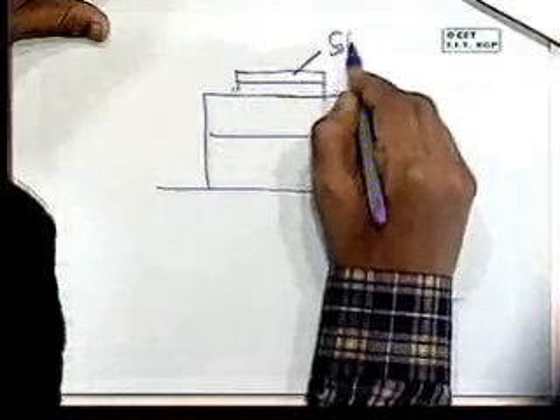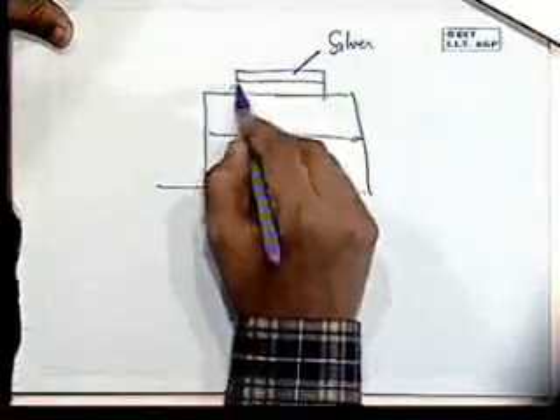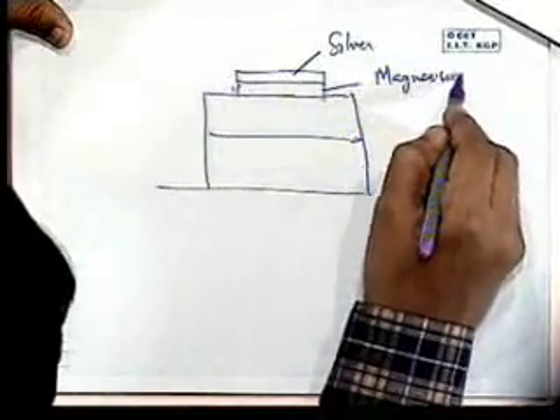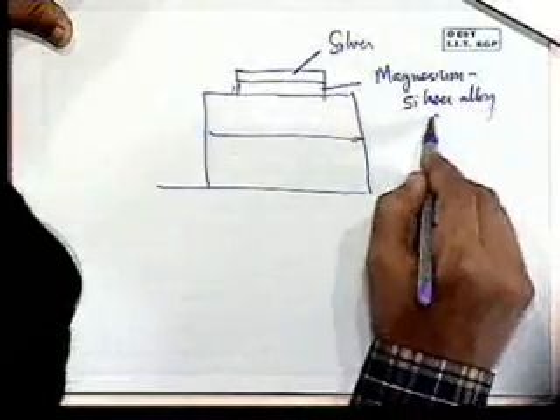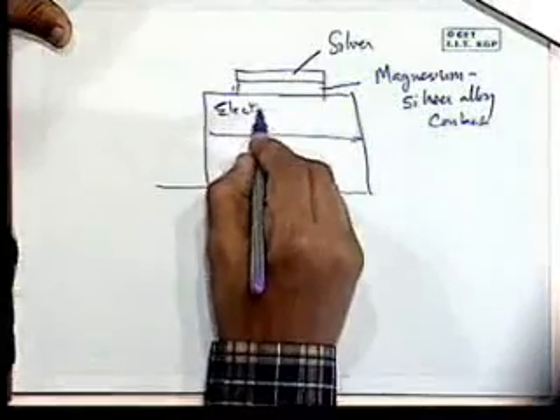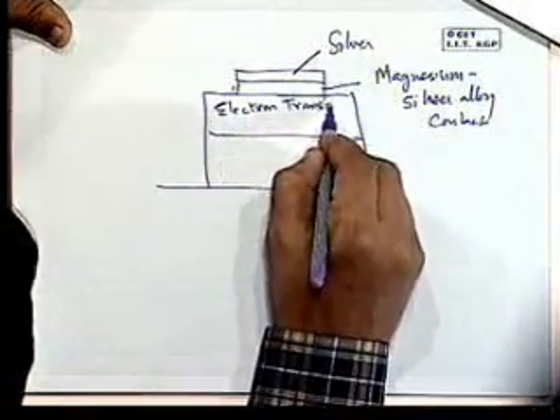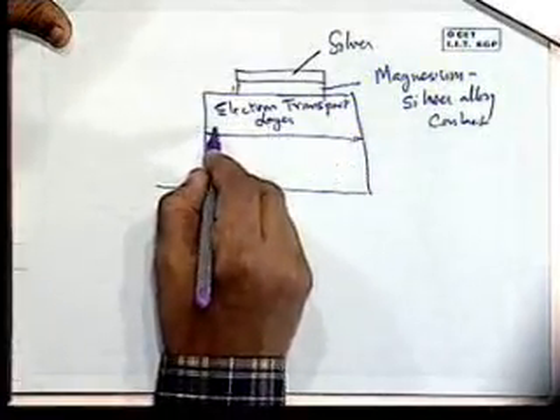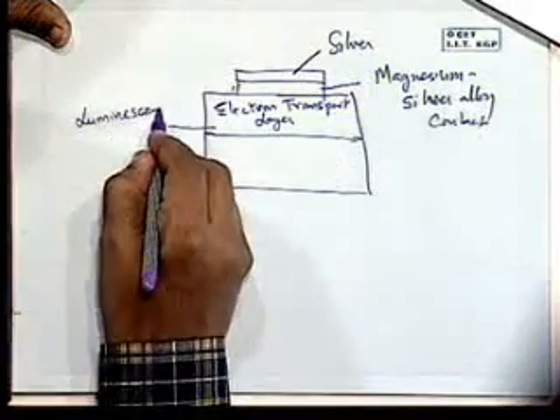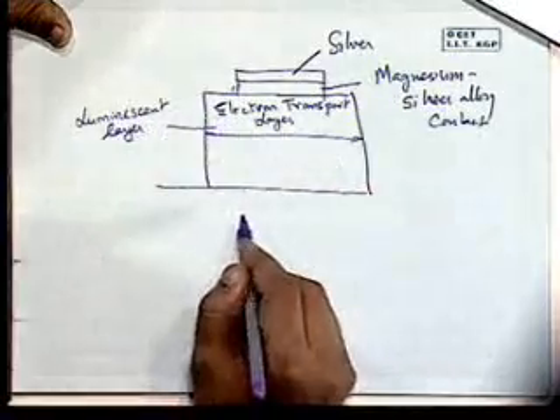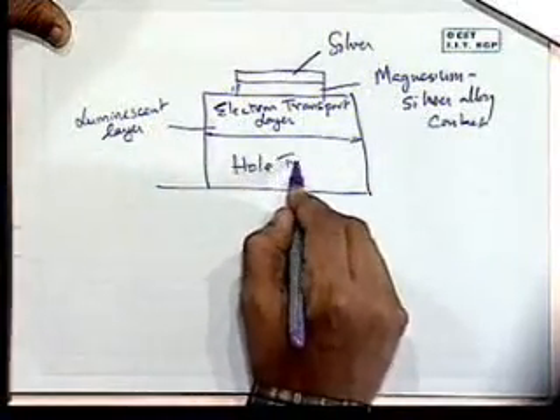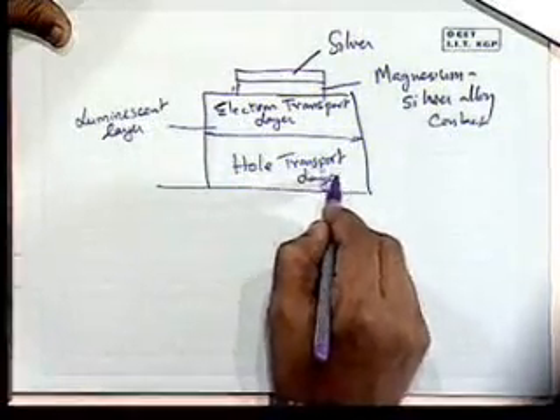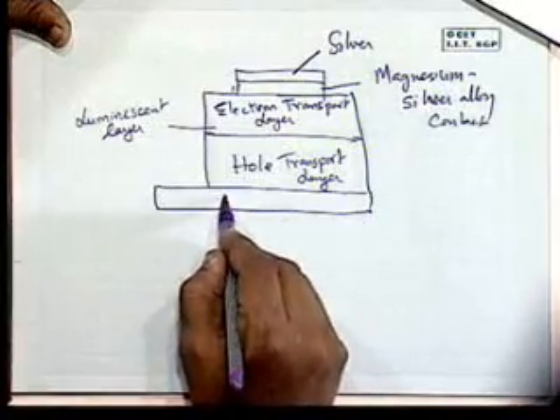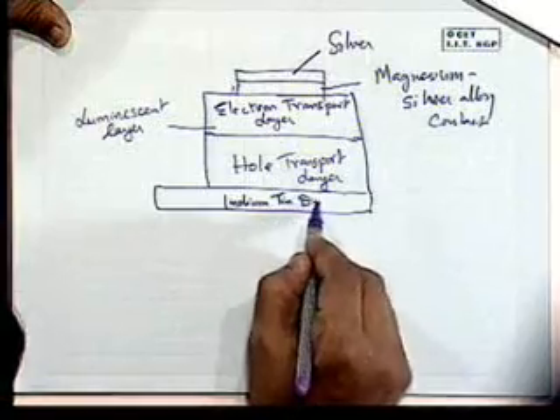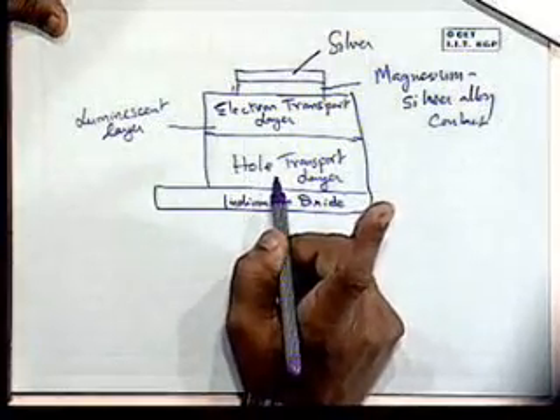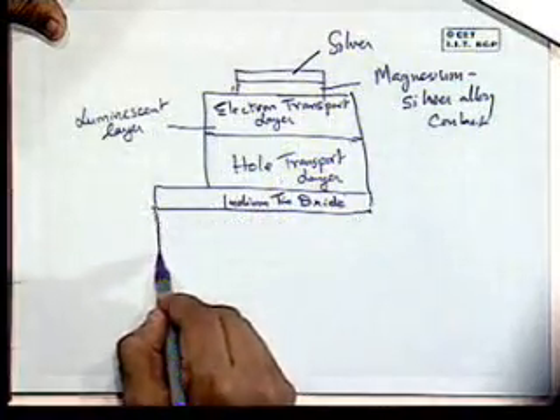You've got silver paste kind of tip over there. This is a magnesium silver alloy contact. This is called the electron transporting layer, ETL. In this particular case, it is also combined. In some cases you may have a separate layer called the luminescent layer, but here it is both the electron transport layer and the luminescent layer. Below it you've got what's called a hole transport layer. Indium tin oxide as the bottom contact. Indium tin oxide is transparent and conducting, that's why it's used as a bottom contact there. And the whole thing sits on a glass slide.